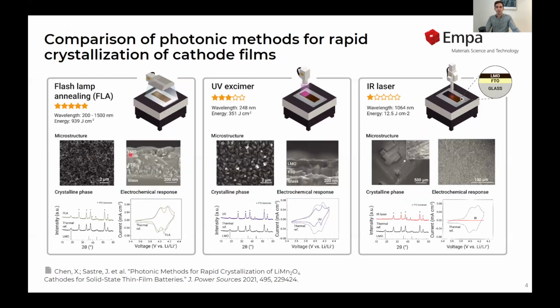Here we have a comparison of the three techniques. We assessed these techniques based on three properties of the processed films: the microstructure, the crystalline phase, and the electrochemical response of the cathode. We gave an evaluation to each technique based on these properties and performance. We observed that flash lamp annealing is capable of delivering as good results as thermal annealing, whereas IR laser cannot crystallize properly the cathode films. UV excimer laser does produce some crystallized films, but not as good as the thermal references.